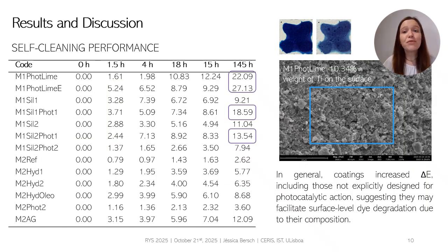This table is related to self-cleaning performance, and it shows color variations for all the studied systems throughout UV light exposure time. These color variations compare color coordinates obtained at different time steps with those obtained just after staining. If we consider 145-hour results, we see that the lime-based photocatalytic paint led to the highest performance, the highest degradation of the dye, followed by the photocatalytic 1 aqueous solution. On the surface of the lime-based photocatalytic coating, around 10% of the weight corresponds to the titanium element. In addition to that, we observed that some color variation was also obtained with other types of coatings, not only the photocatalytic ones, in lower extents, of course, but this could be related to their composition.